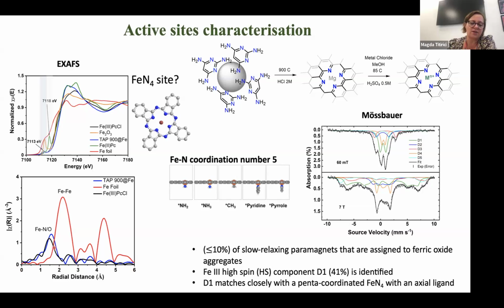And you see how nicely your catalyst is matching with this iron phthalocyanine, which tells you that you have the single atomic site configuration mostly. You could also do extended X-ray absorption fine structure spectroscopy, and here you could learn about the coordination number on your site, and this also gives us a coordination number of 5.